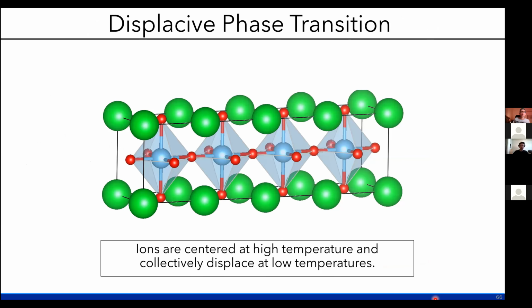And so I personally want to understand the characteristics of the phase transition because we want to understand how this phase transition is related to the superconductivity. And when I say a phase transition, all I'm talking about is going from the state where the material is not ferroelectric to the state where it is ferroelectric. And there are two basic ways that this can happen. So here I've shown 4 repeated units of the material just to demonstrate this behavior. So in a displacive phase transition at high temperatures, all the titanium ions are centered in the unit cells.